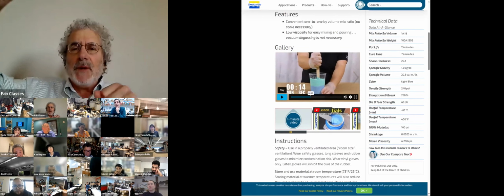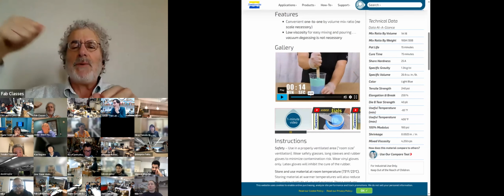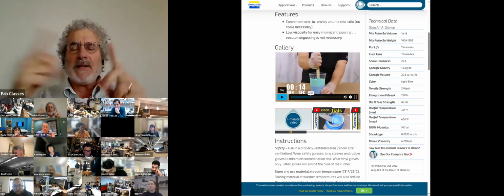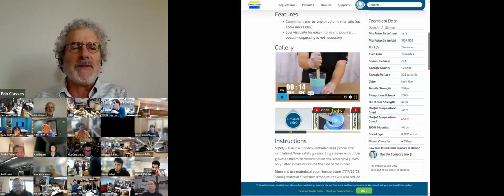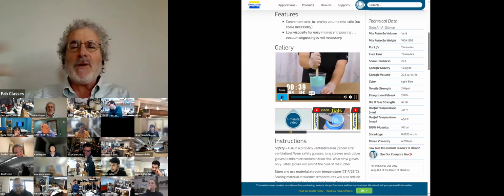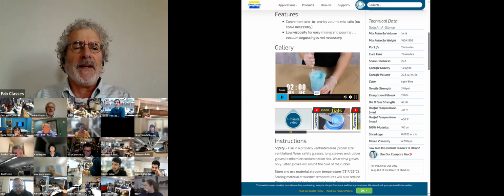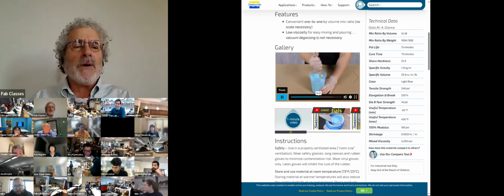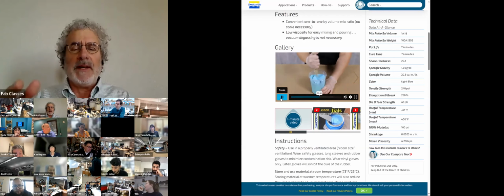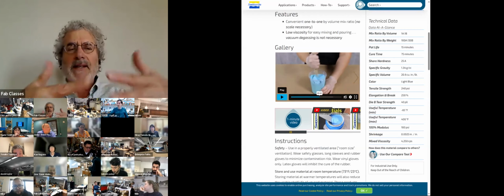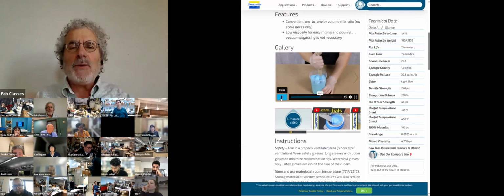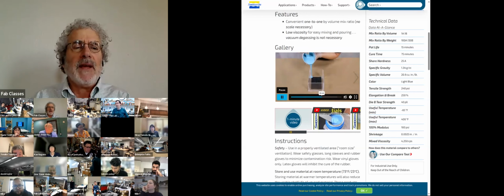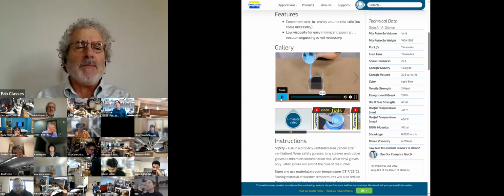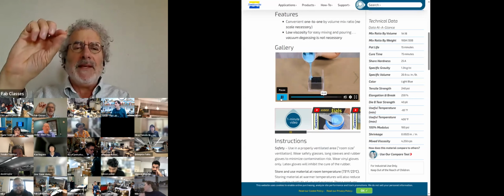Now here comes a key step. When you stir, you don't scoop, because if you scoop, you're driving air in, and air makes bubbles, and that's one of the banes of this week. So the stirring is shearing, not scooping. So you shear to stir, you scrape around the edges to make sure you're getting everything. And this goes longer than you think. It's quite a few minutes. When you start, it's striated. You keep going until there's no striation, until it's uniform. Then you don't dump it in the mold. You pour it in a thin bead.